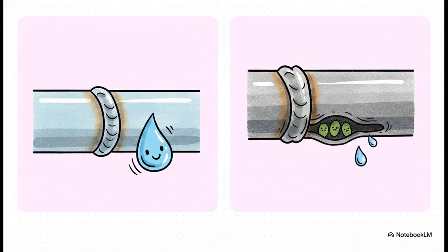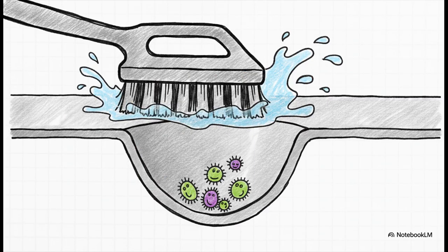Proper sanitary welds must be flush ground or slightly convex, almost always done via full penetration TIG welding. Contrast that with your standard structural defects like overlap or undercut. Those instantly create microscopic hiding spots. Let's talk specifically about the danger of concavity. If your weld profile is concave, you inadvertently create what I call a microtrench right at the toe of the weld. Now sure, it might hold together under pressure, but your cleaning solution simply cannot reach deep into that trench.